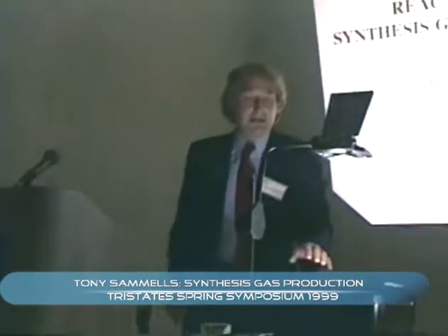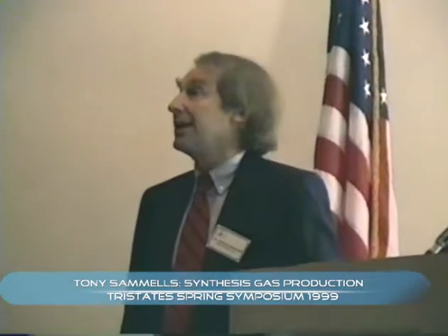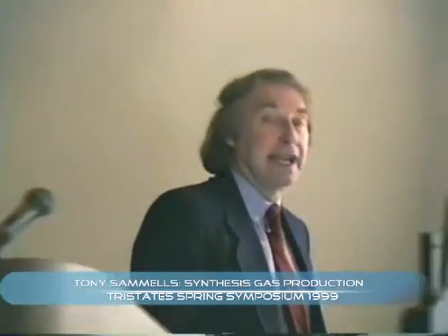Really, the point I want to get across in this presentation is the fact that although we do not have electrodes in the conventional sense of electrochemical technology, the basic principles which govern this dense ceramic membrane technology, and the chemical processes which are occurring on each surface of the membrane, are in fact electrochemical in nature. Although in the case of converting methane or natural gas to synthesis gas, or converting methane into ethylene, or converting H2S to sulfur and water, or any of those kinds of processes, they are, in fact, thermodynamically downhill, spontaneous processes which do not require the use of any electrical energy.